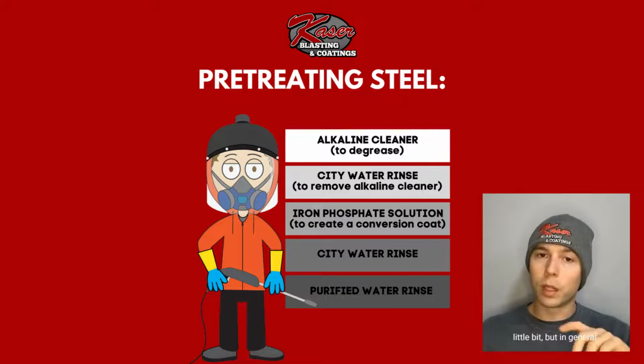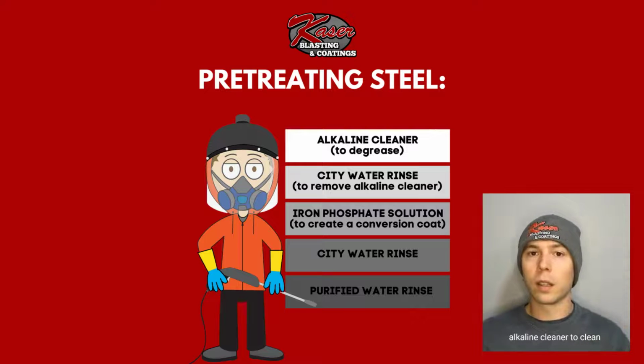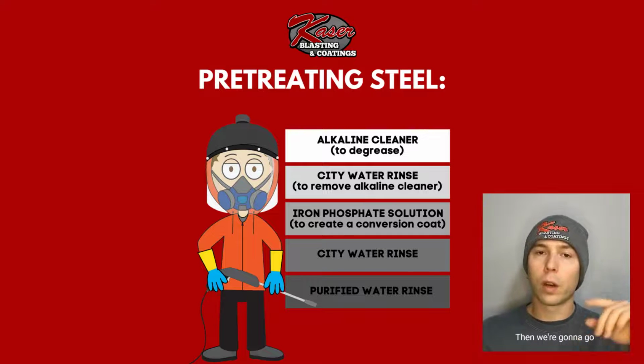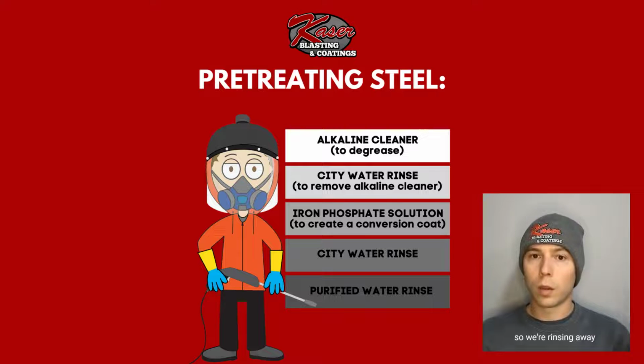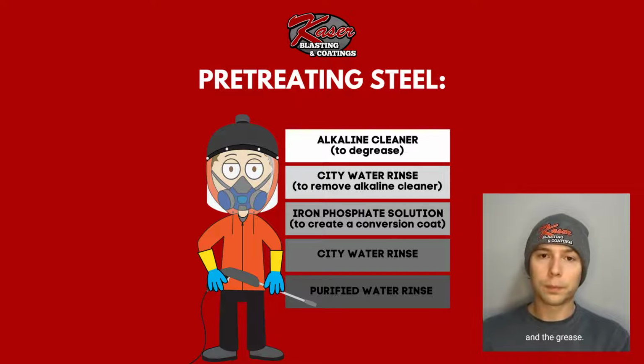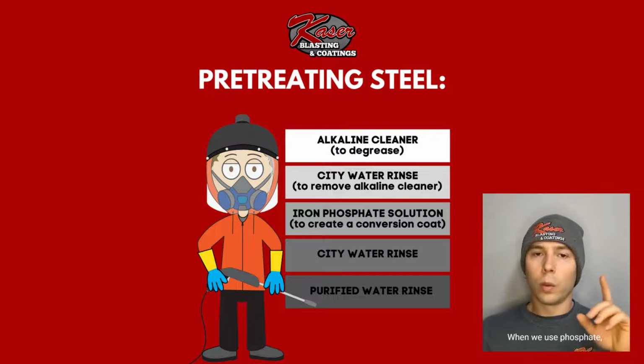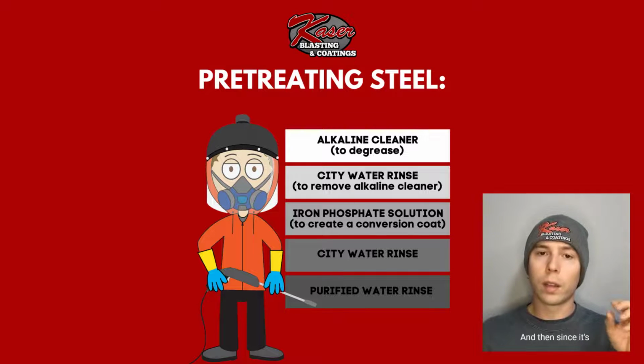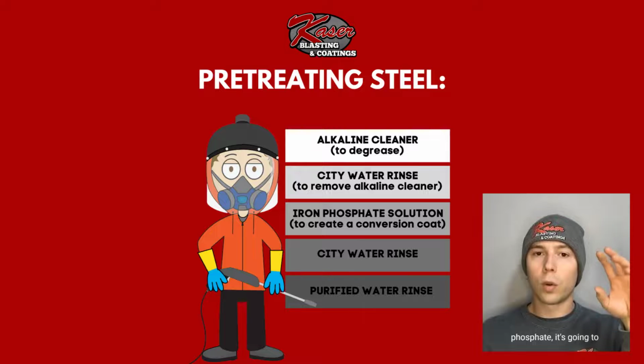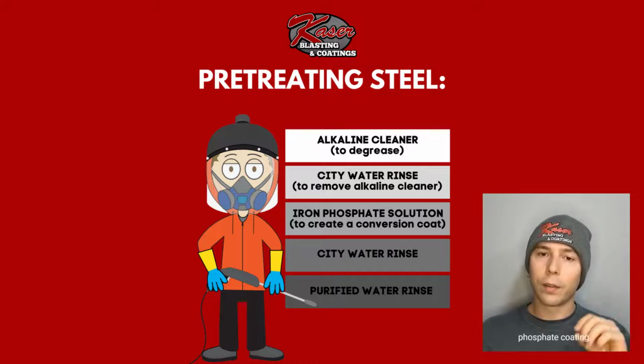This could vary just a little bit, but in general, we're going to start with a degreaser, some sort of alkaline cleaner to clean off the greases and oils. Then we're going to go into a city water rinse. So we're rinsing away the alkaline cleaner, the oils and the dirt and the grease. Then since we're on steel, we're going to use a phosphate. When we use phosphate, that's an acid. It usually has a little bit of a cleaning package in it still, so it's going to clean the parts just a little bit more. And then since it's phosphate, it's going to start having a chemical reaction with the steel substrate, and you're going to create an iron phosphate coating.